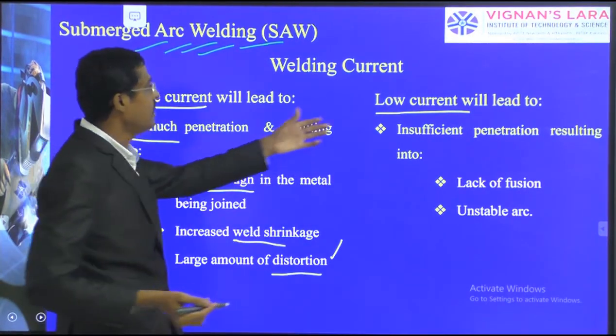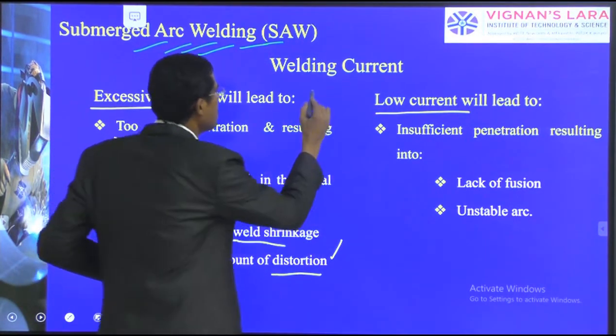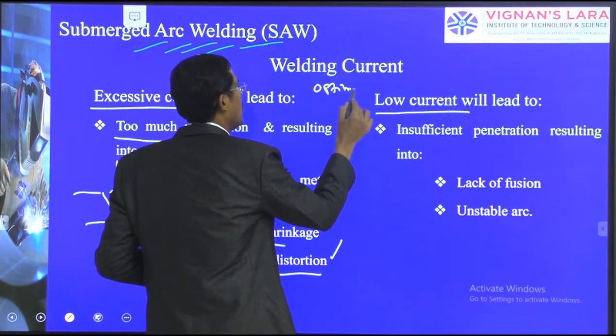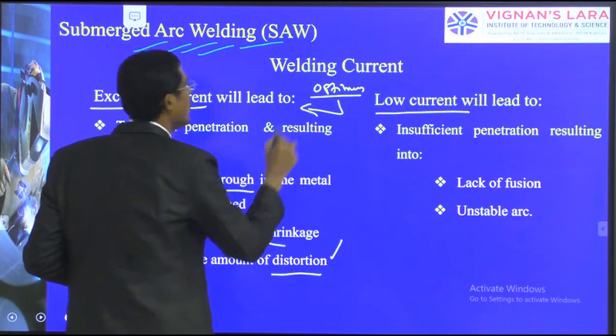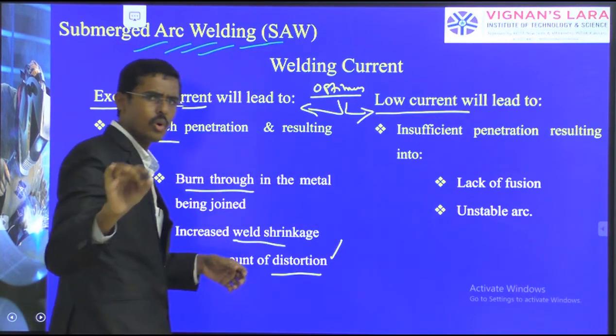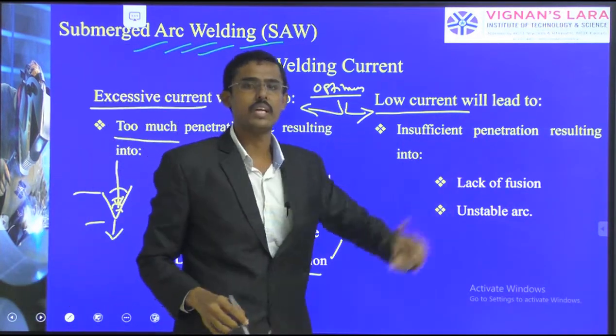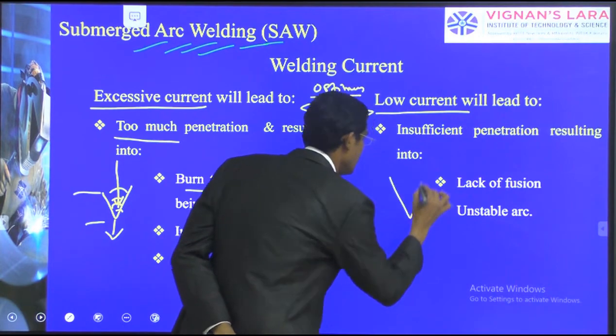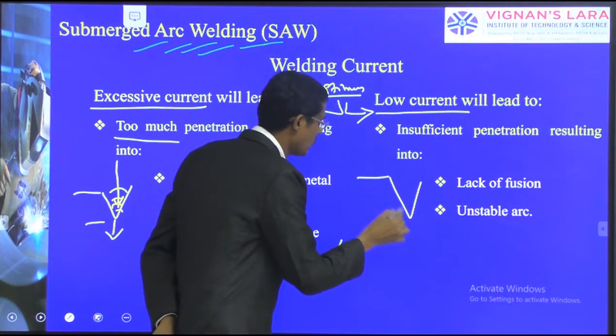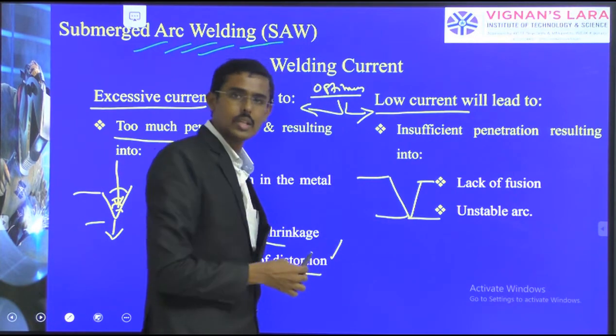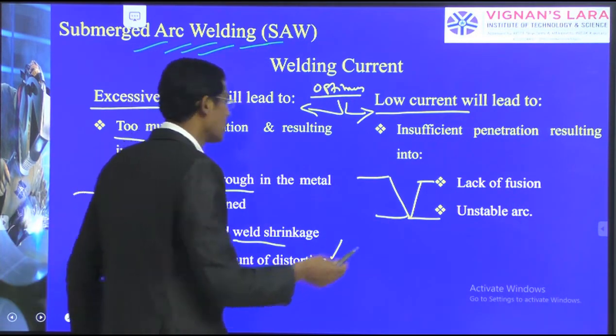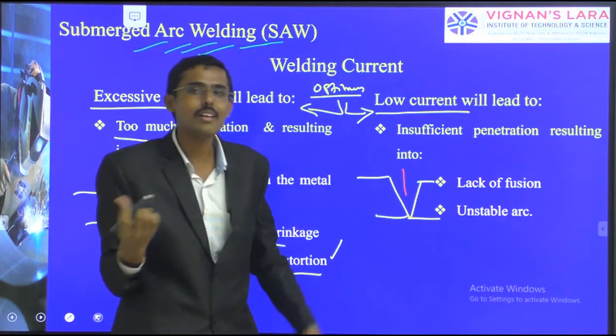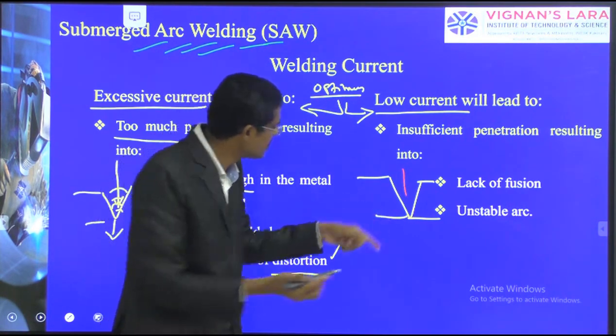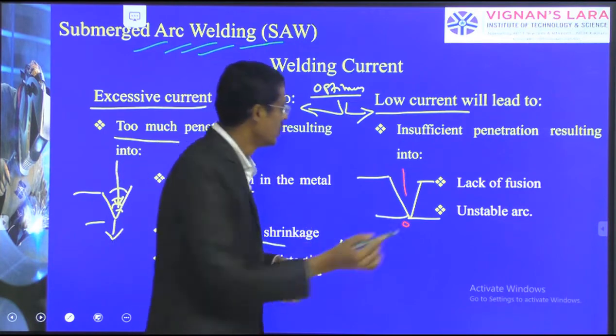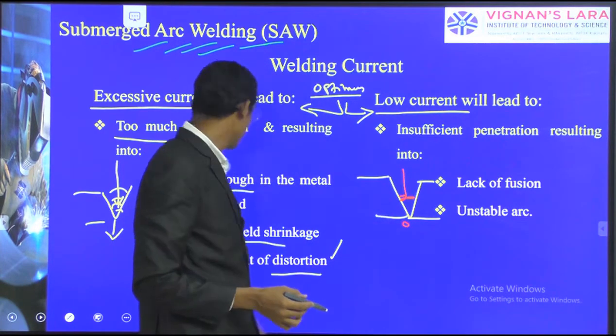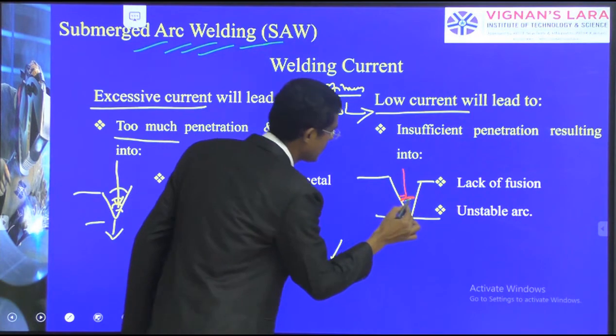Now instead of the optimum current, I am going with too low. What happens with too low? Insufficient penetration. What is this insufficient? Here is the V groove, and this is the total length we have to weld, and I am welding. It reaches up to this condition only. It is not melted. Then how will it reach the root? So welding stops here itself. So here is the gap which is not melted.